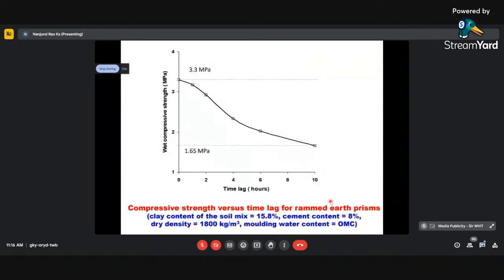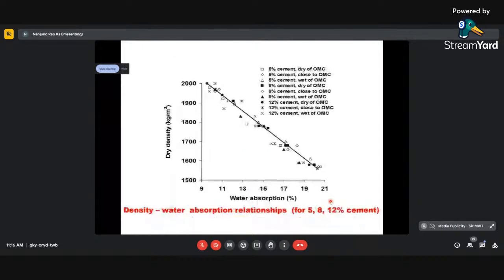If you don't do it, what happens? You can see this next slide. The compressive strength, the wet compressive strength, immediately after mixing the soil, if you ram, you get 3.3 megapascal. Let us say after 10 hours, you mix the materials, put water also, don't put it in the mold and ram. Then the resulting specimen, if you ram it later after 10 hours, you are going to achieve a very small wet compressive strength, 3.3 megapascal to 1.65, it almost drops by 50%. So the importance of ramming the material immediately after adding water is shown in this graph.